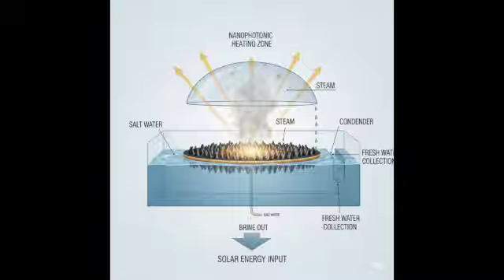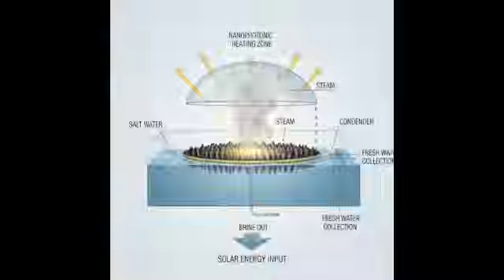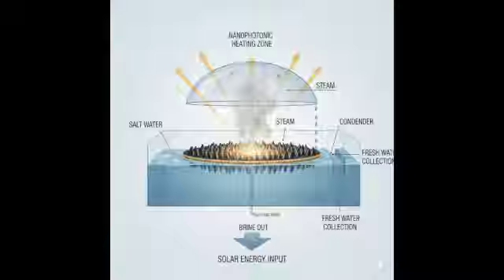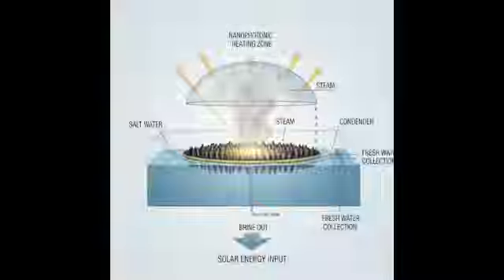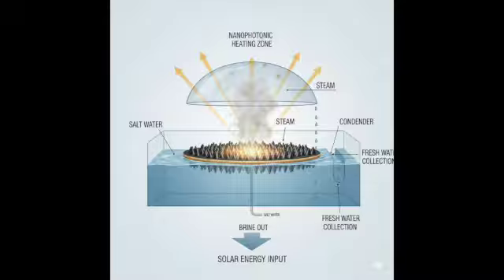Lower velocities, why? Because a lower velocity gives the water more residence time in contact with the heated photothermal surface. This allows sufficient time for the localized solar heat to be absorbed and to establish that strong reverse temperature gradient needed for efficient evaporation. So slow flow allows the surface to get properly hot relative to the bulk. Precisely. If the water flows too fast, it might not get heated sufficiently at the interface before it moves on. The engineering implications here seem huge. Lower feed velocity means smaller pumps, less energy spent on pumping.